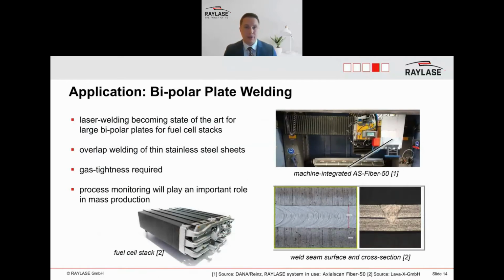Another very important application for us is the welding of bipolar plates for fuel cells. We see that this process is becoming the state of the art for large bipolar plates for the fuel cell stacks, especially for the PEM fuel cell stacks, where you have an overlap welding of two stainless steel sheets that have to be welded together. The requirements are very high here. The joints have to be gas tight in order to, well, not have the hydrogen and oxygen leave the fuel cell, basically.